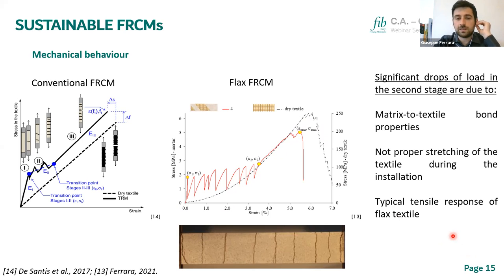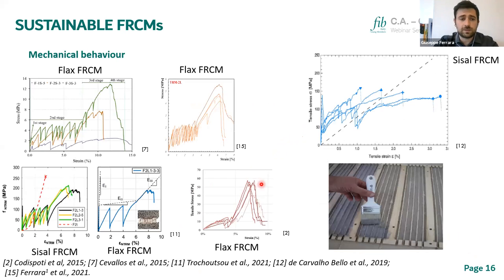So of course we can see that in order to have a mechanical behavior that tends to be similar to the traditional one, we have to do something to improve these materials. And this is mainly what I've been seeing in literature by observing several studies in which, for example, either by using sisal, sisal flax, or other types of materials, and also by increasing the textile amount in the mortar, the response is always the same. I would like to focus the attention on this work, where we can see the hardening phase of the system starts at lower strain values.